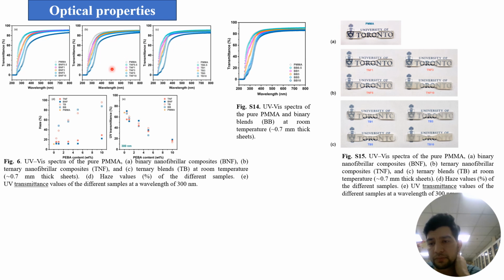These figures show the material up to 3%. These results show that the material, up to the different concentrations, shows different colors. So up to 3% fibers are nearly transparent. If the composite contains 3% PEBA, it is as transparent as PMMA in the visible light region, about 500.